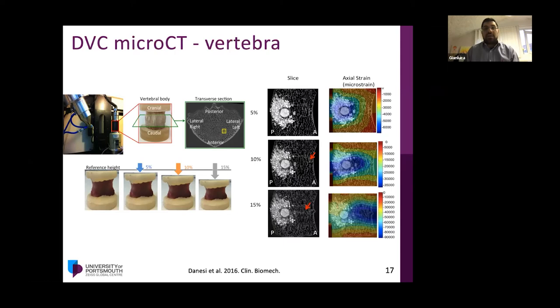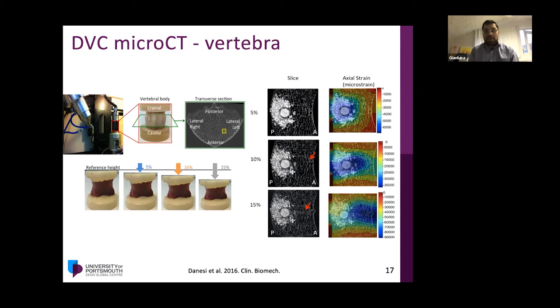Another interesting study used prophylactically augmented vertebral bodies. It's very interesting to observe how strain shifts from the cement part of the sample to the external cortex, promoting fracture there. This tries to answer questions about where load bearing is occurring in augmentation and how the load transitions from cement into bone, with eventual fracture of the bone.